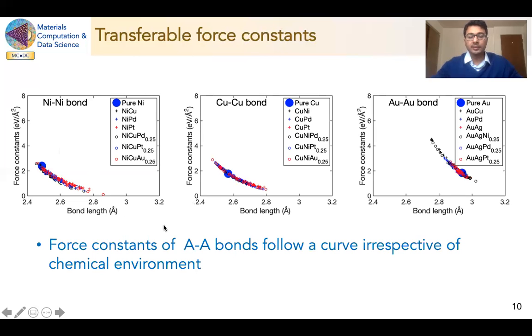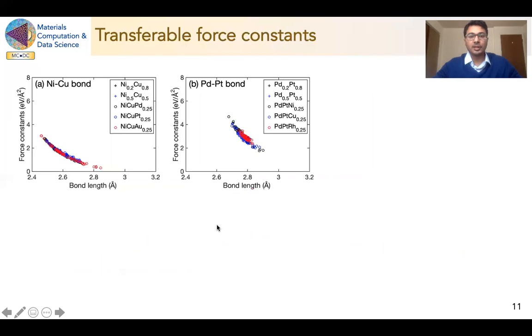Similarly, in some other cases, for example, the copper-copper bond and gold-gold bond, the force constants again follow the same curve. This shows again that the force constants are transferable to different chemical environments, which is a unique observation. Now, similar trends we have observed in the case of AB type bonds also. As you can see in these two types of bonds, one is the nickel-copper bond and the other is the palladium-platinum bond, the force constants again follow the same curve, although these bonds are present in different chemical environments in binary and ternary systems.